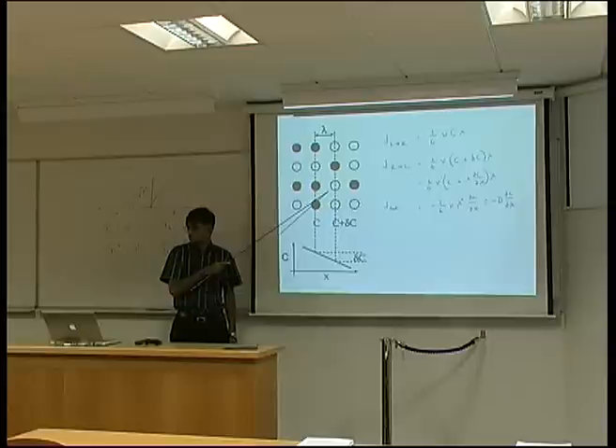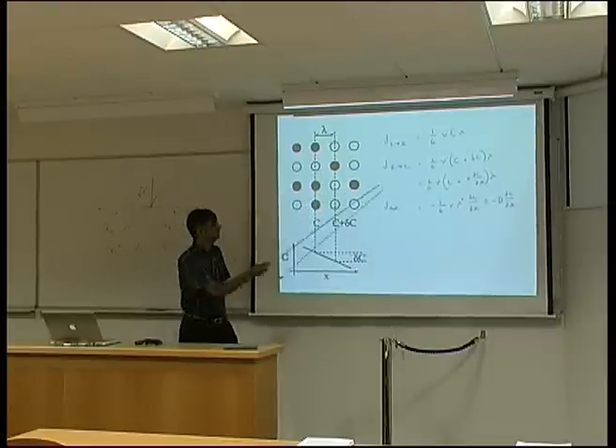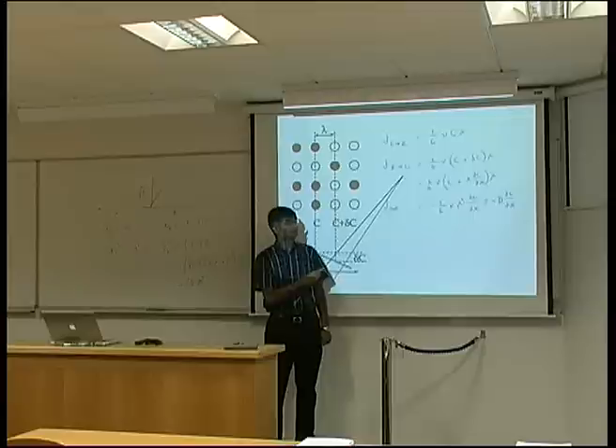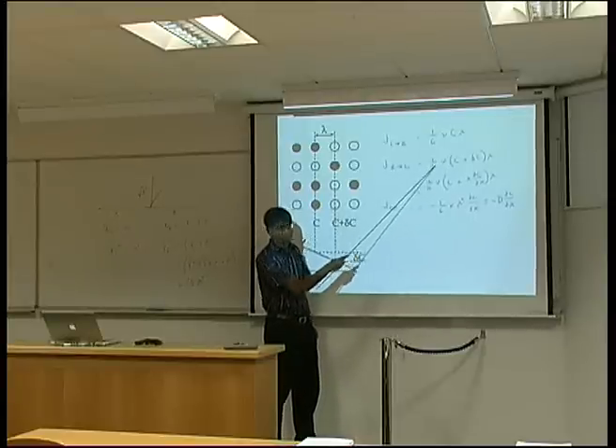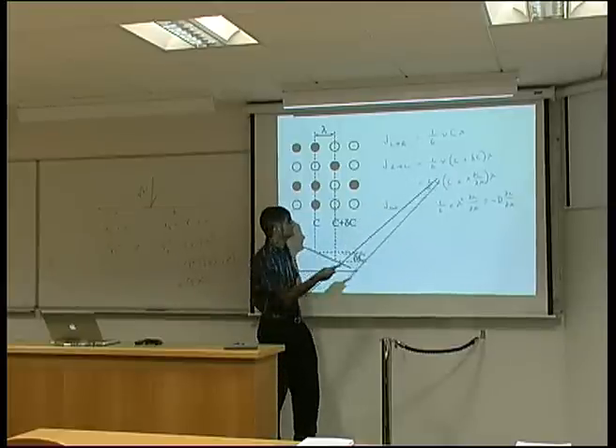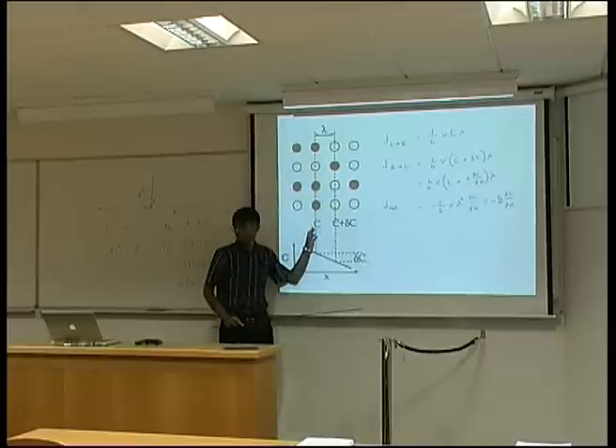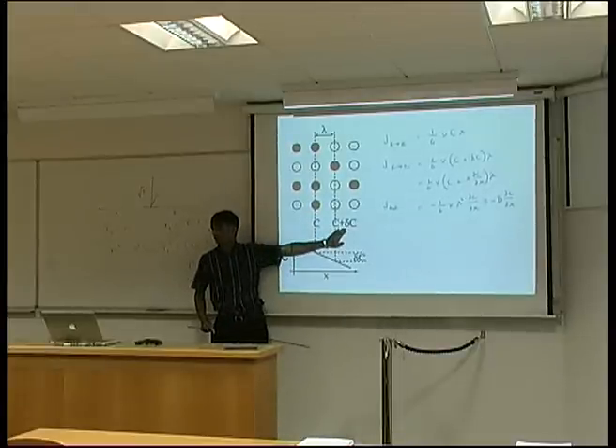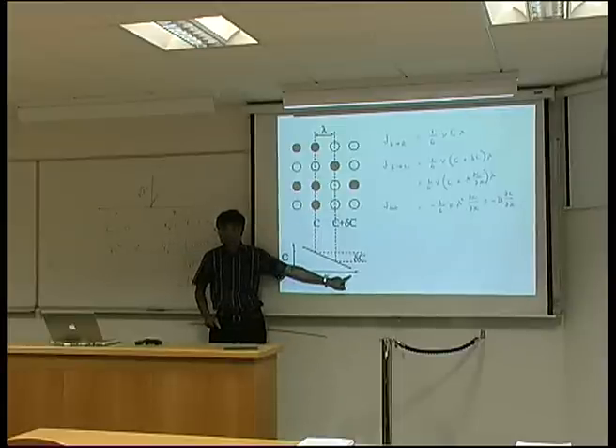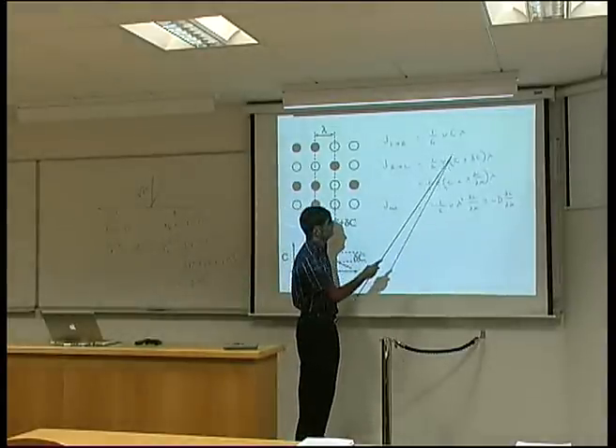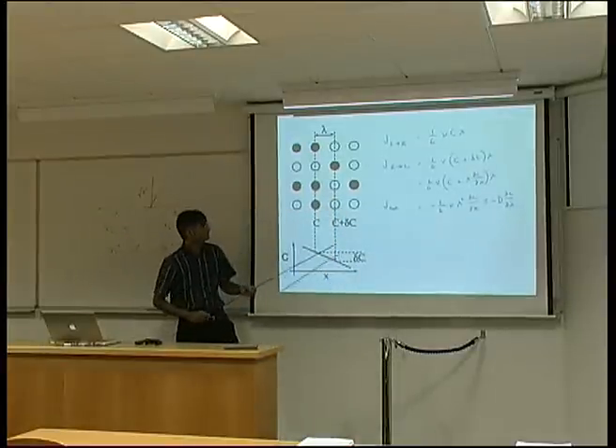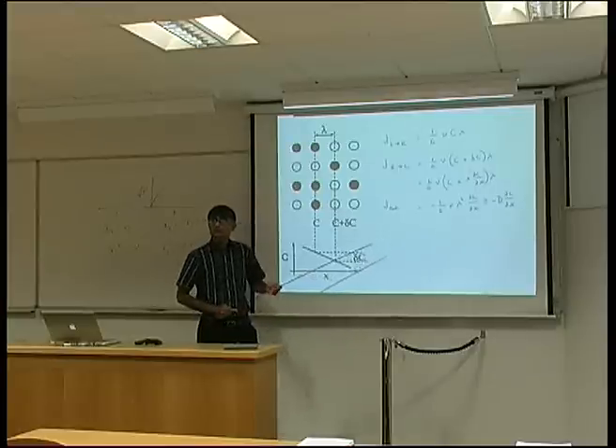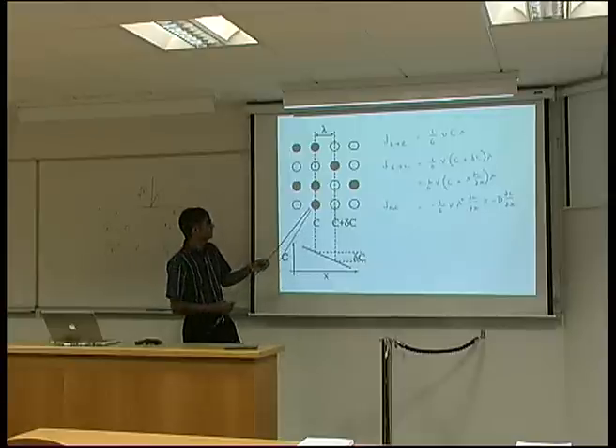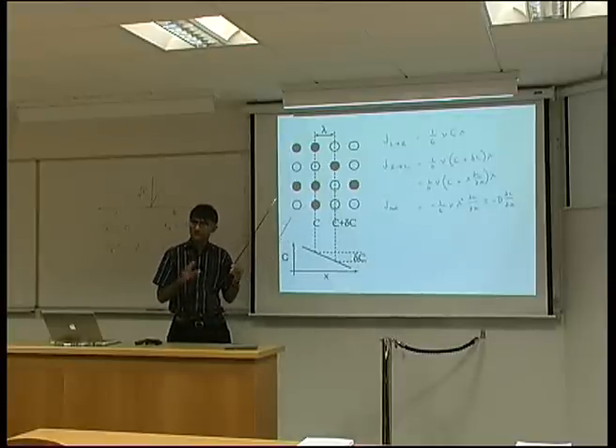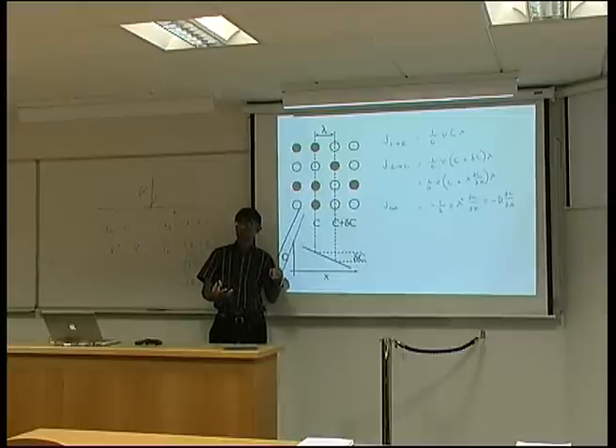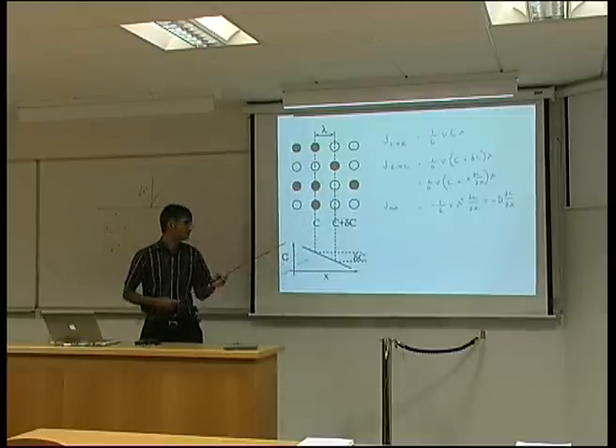I have to take account of atoms which are jumping back as well. And therefore, I have another flux which is going from the right-hand side to the left-hand side, which again has the effective jump frequency along the minus x direction. Now the concentration here is different from the concentration here. It's changed by this value delta C. You can see that from this graph. So this represents the number of solute atoms in this plane. This filled circle is atoms. The empty circle is a vacancy, but there are no vacancies here at the moment. I just want to highlight that there are two species of atoms, two different types of atoms.